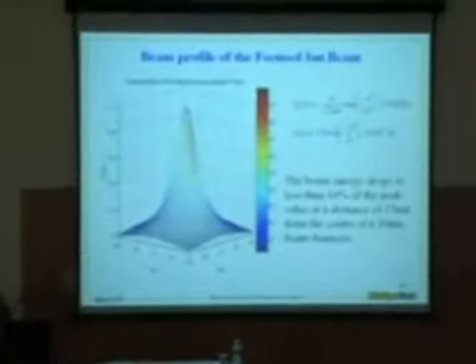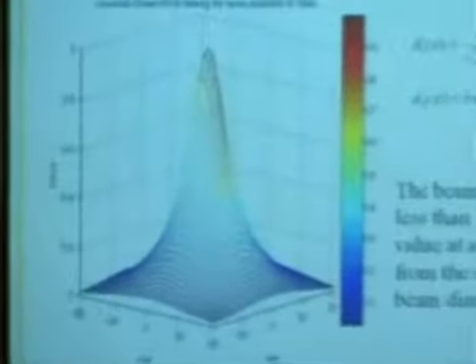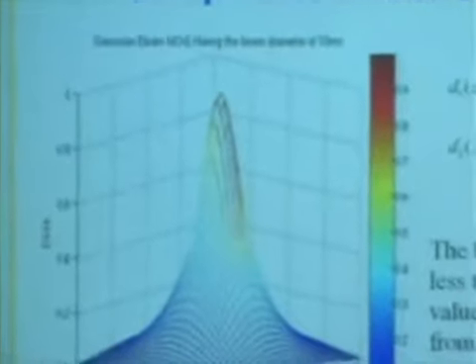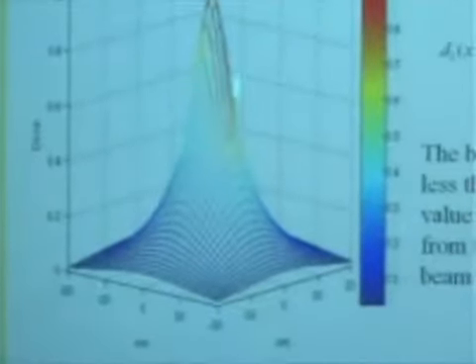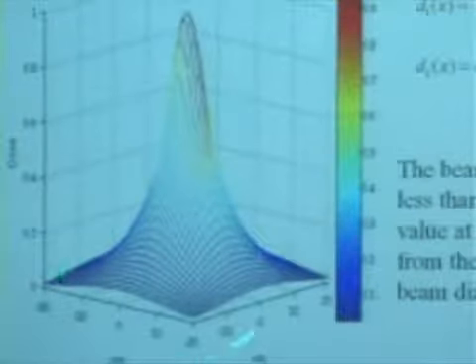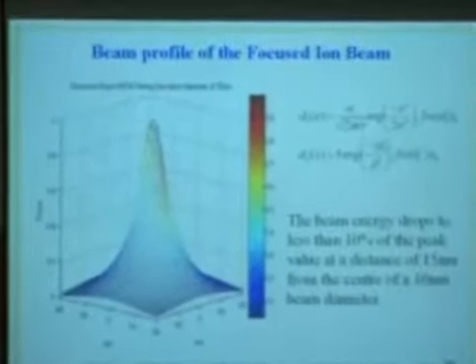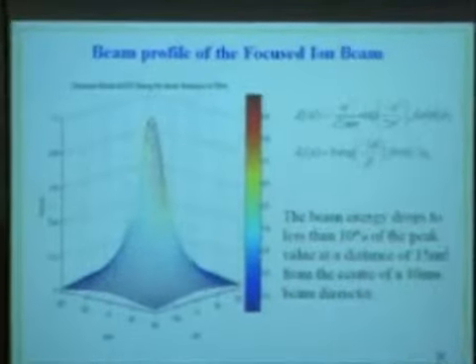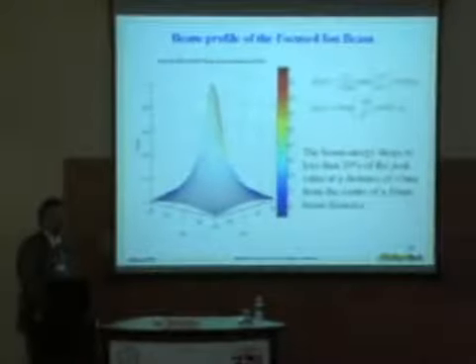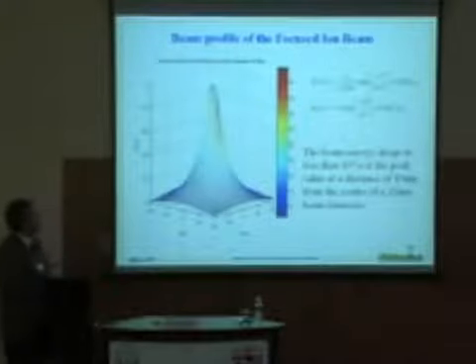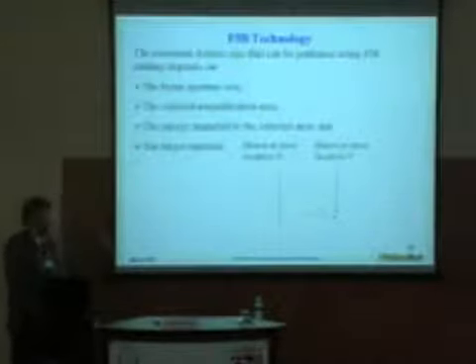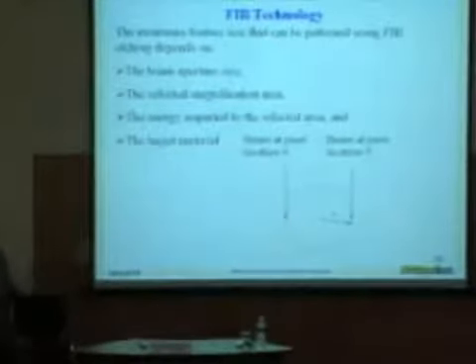An alternative path where we wanted to understand what were the limitations of the process technology, what were the limitations of the beam etching. The focused ion beam has an error function profile near its tip with a Gaussian tail. And this is a profile that has been characterized really over the last decade by the manufacturers as well as by several researchers around the world. That profile results in a significant amount of energy and a significant dose of ions that extend far beyond the nominal full width half max feature profile, which is what is stated. So we wanted to look at how small can we actually go with this technology, and what are the implications of doing this etch.